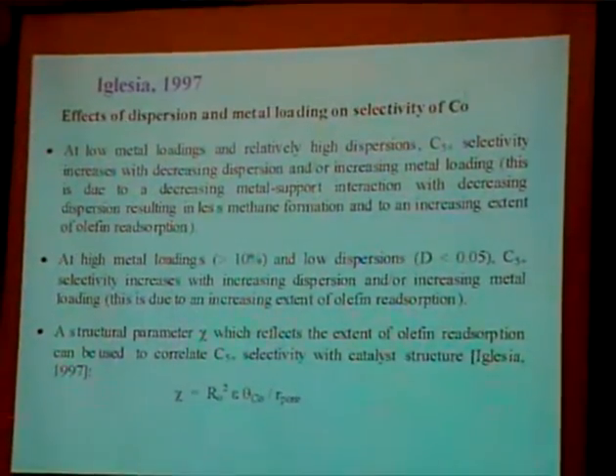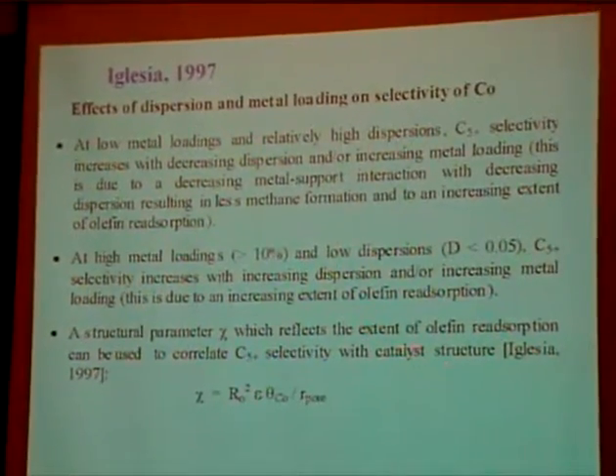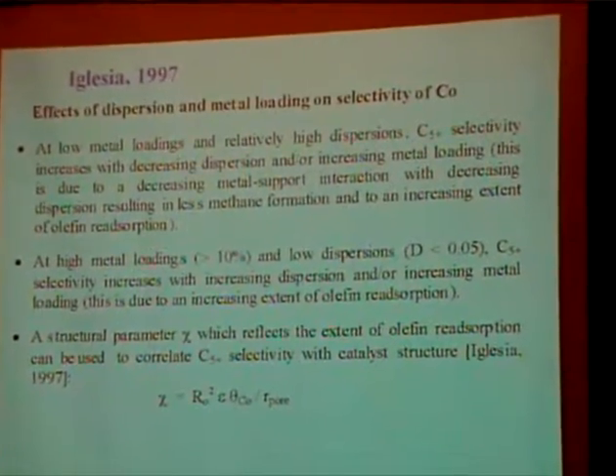In fact, these workers developed a structural parameter chi, which reflects the extent of olefin readsorption that can be used to correlate C5 plus selectivity with catalyst structure.